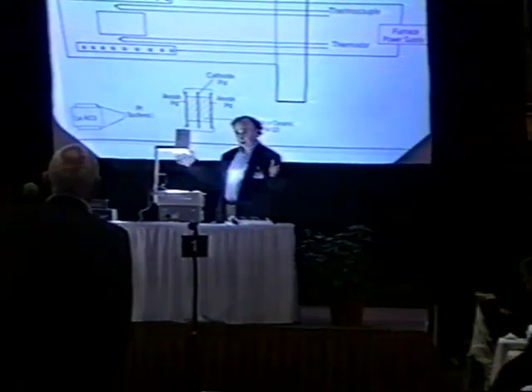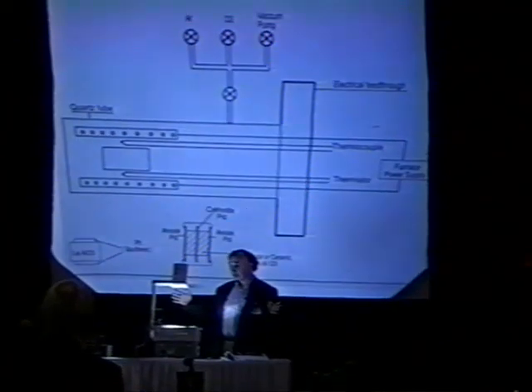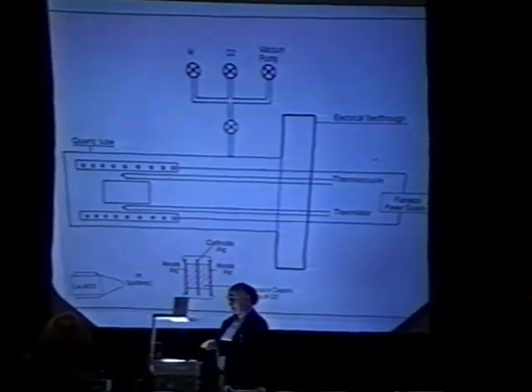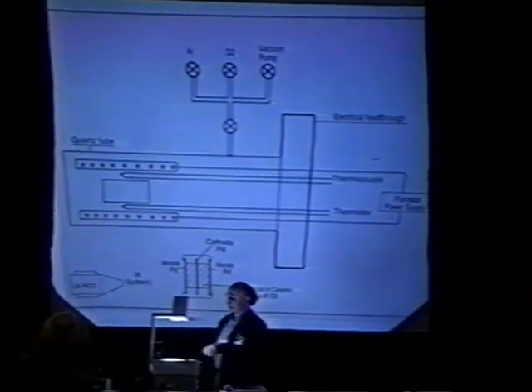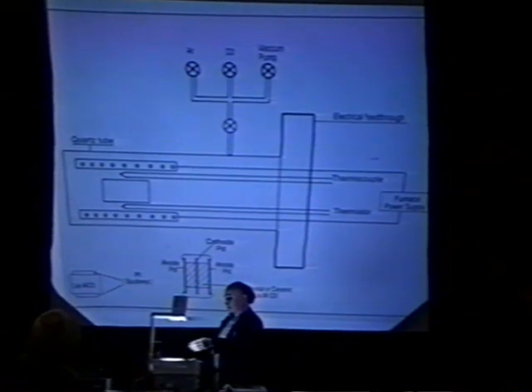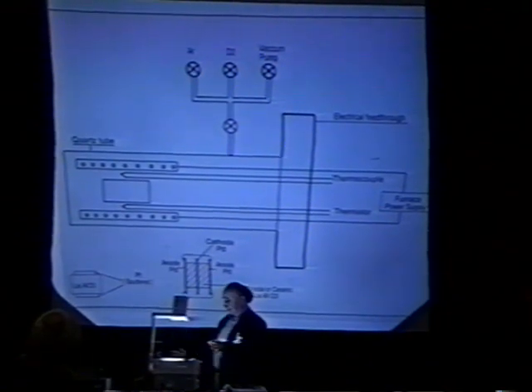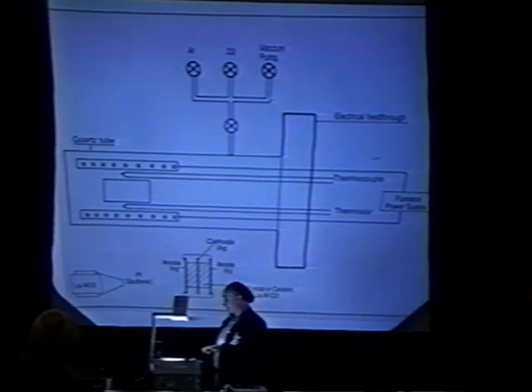I didn't mention that because I didn't make a transparency for it, but I can explain it. In order to get this high stability, we had to put everything in the thermostatic box at 90 degrees. That made the system extremely stable. The outside temperature was constant. The heat flux was constant. And we had all the electronics stabilized. So we're pretty sure everything is correct.